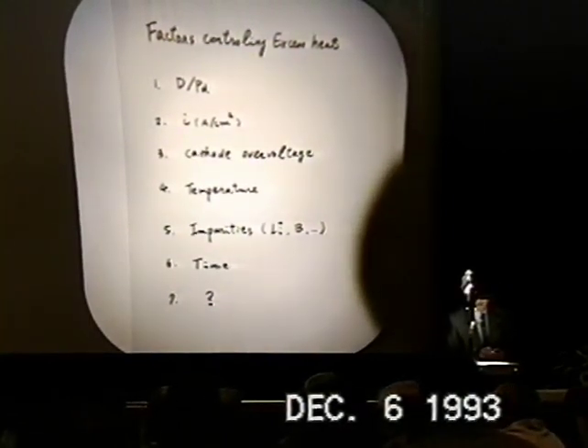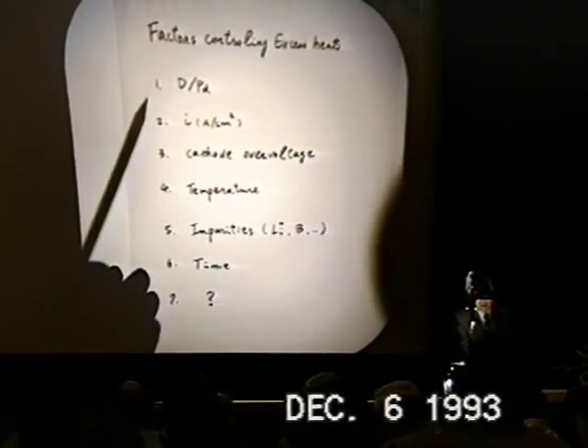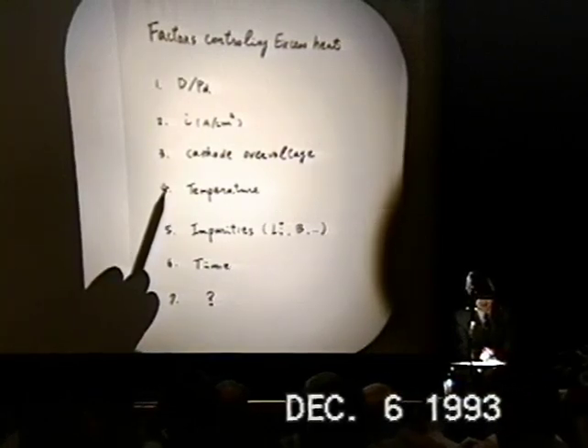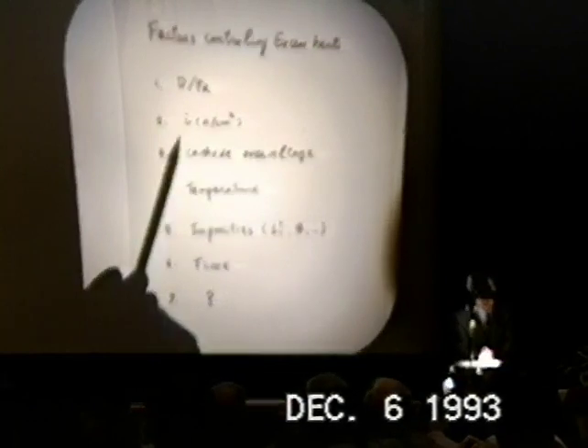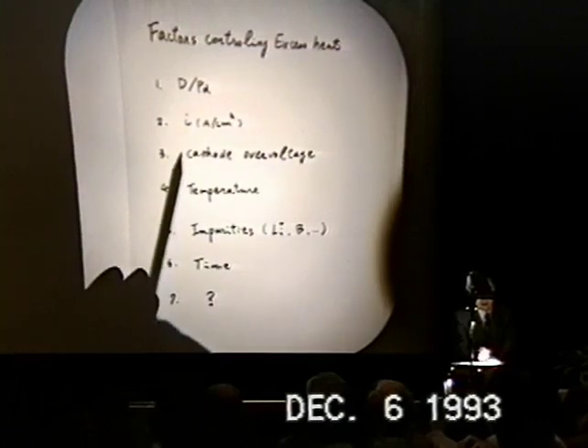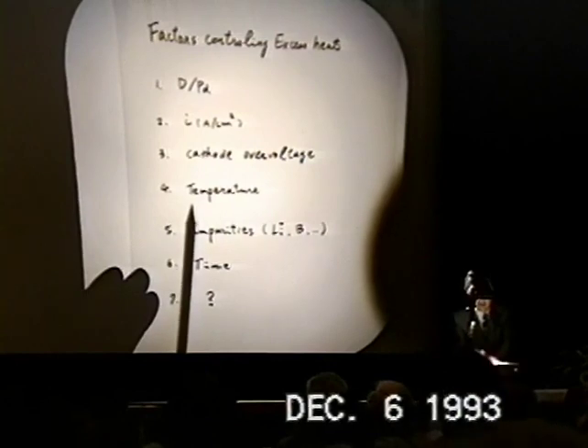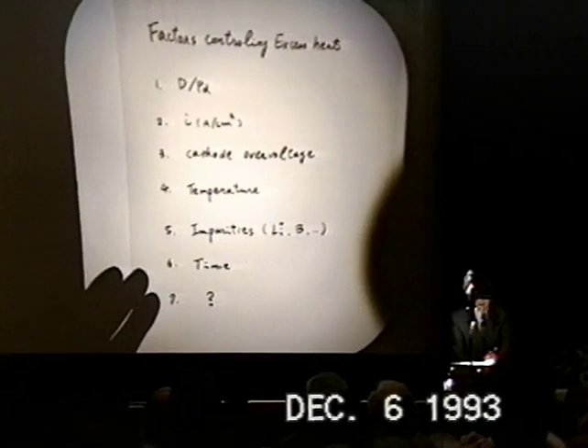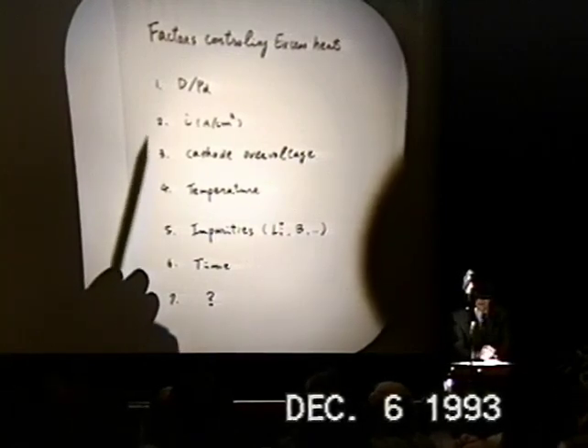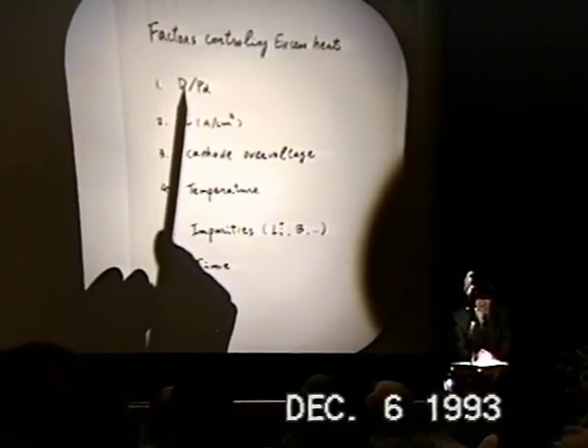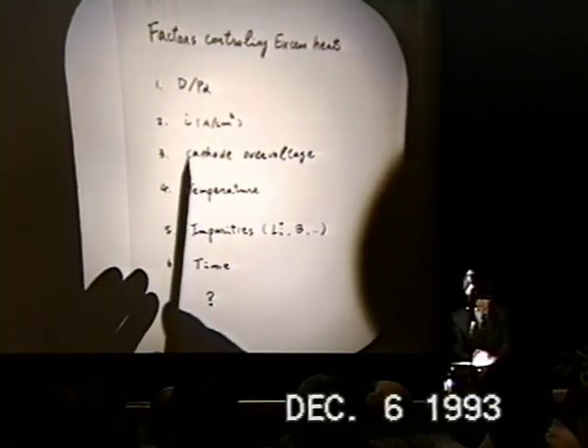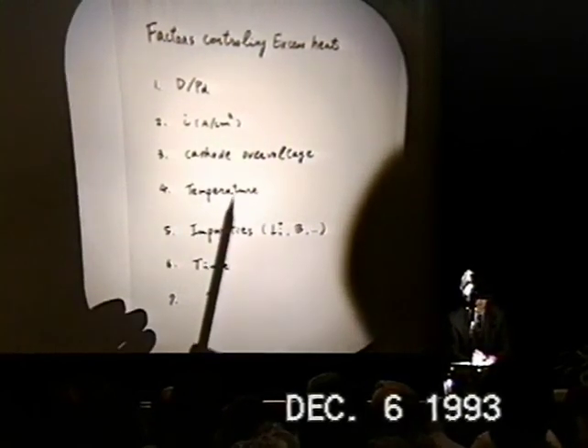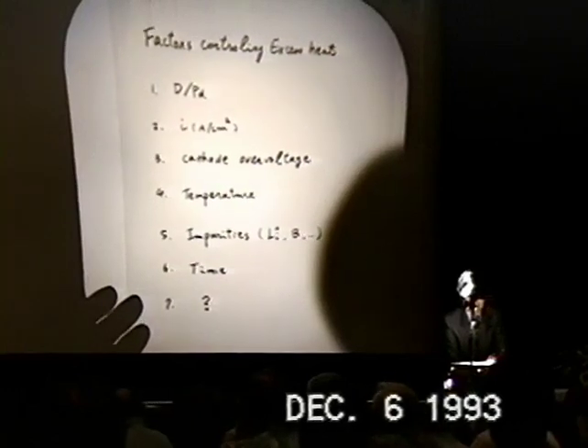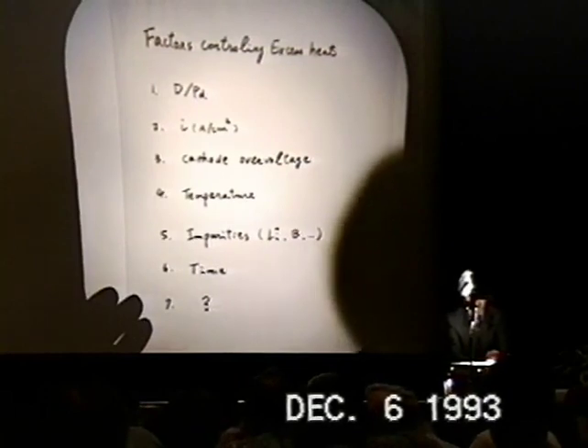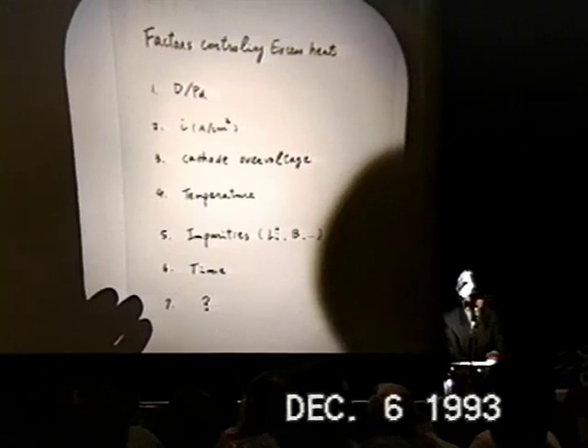So we would like to investigate the effect of these parameters systematically, but the unfortunate condition is that numbers 1, 2, 3, 4 are not totally independent in our experiment. When we apply current, it determines deuterium loading ratio, and it determines cathode voltage, and it even determines, in many cases, the temperature in the electrolyte. So we are thinking that it will be better if we can analyze our data at constant deuterium loading ratio, or constant current, or constant cathode voltage, or constant temperature. So we have 4 variables. Maybe the analysis could be very difficult, but if one of these parameters is really important, there is no reason why we shouldn't do this sort of systematic investigation.